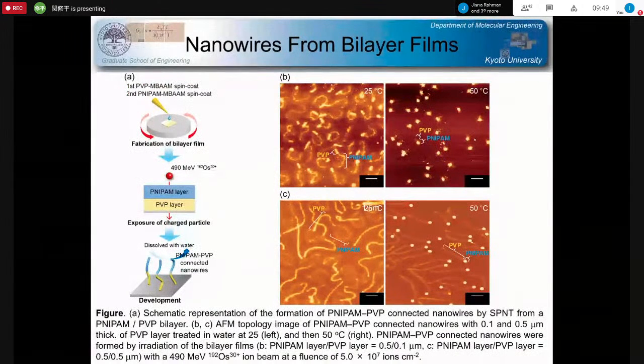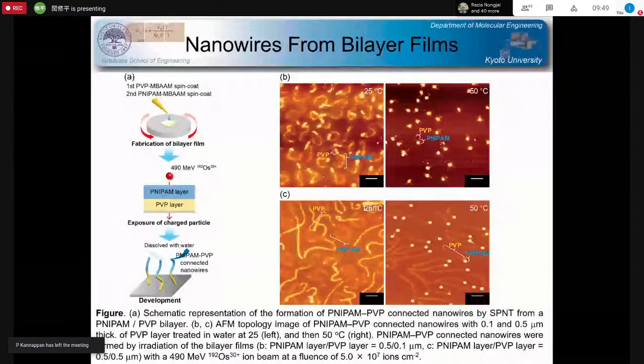And the other interesting feature of this kind of one-dimensional nanowire is its very high feasibility to combine two different kinds of polymer materials into one single nanowire, because the protocol of nanowire formation is very simple. The only requirement is to prepare a thin solid film of organic substances on the substrate. After preparing one layer on the substrate, a second layer is successively overcoated. Again, the ion beam is irradiated vertically, passing through the double-layer solid films. Eventually, along the particle trajectory, double-decker nanowires are generated. And as displayed in these four figures, the double-decker nanowire was clearly observed.